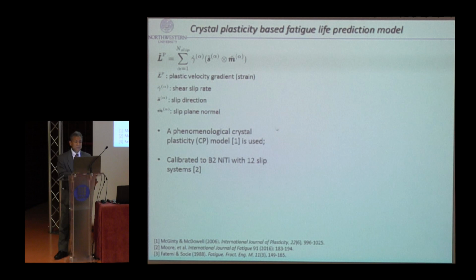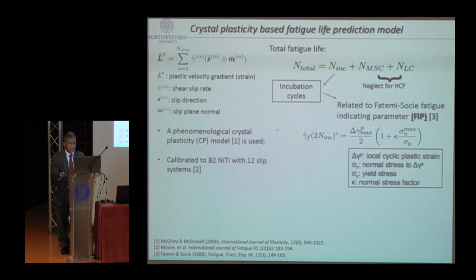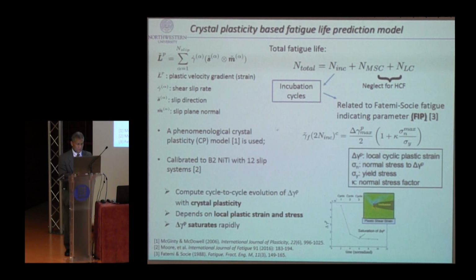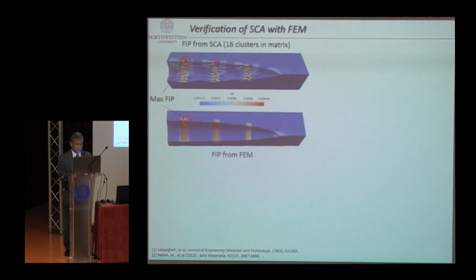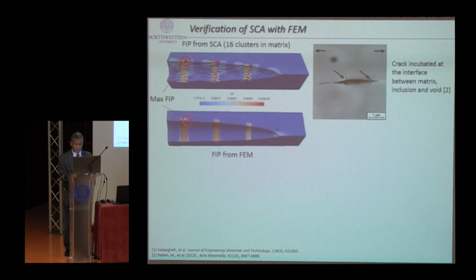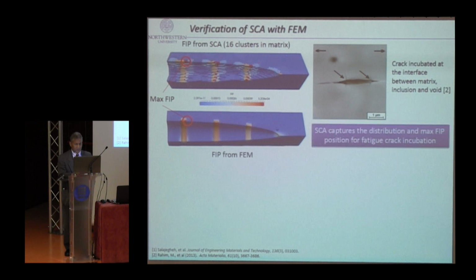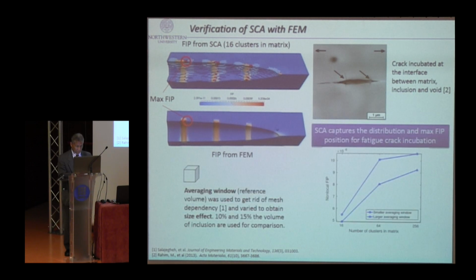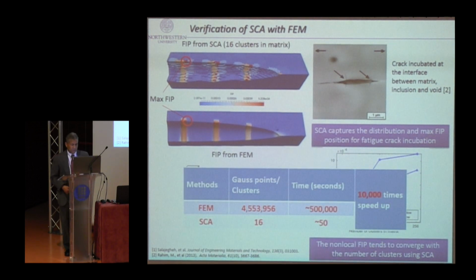So we do a dislocation-based crystal plasticity. These are all based on plasticity. That's related to this topic here. And we are focusing on this incubation period. There's a theory on it here. The question will be how we can actually predict fatigue life in this case. So this is something that we have done. You can actually look at the microstructure of the system. And we apply this SCA method on it. Based on our calculation for this small cluster, we are talking about many degrees of freedom, and we can get a speedup of 10,000 in the computation in this case.